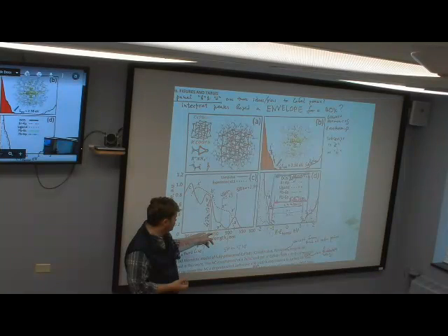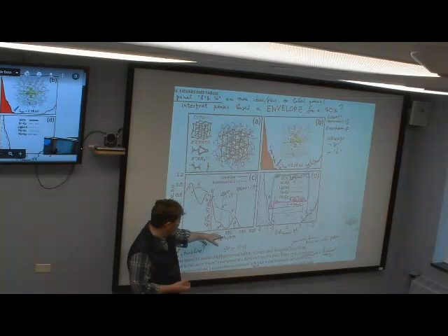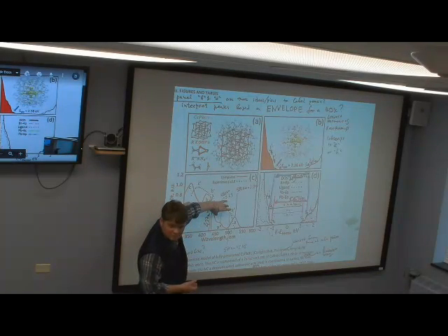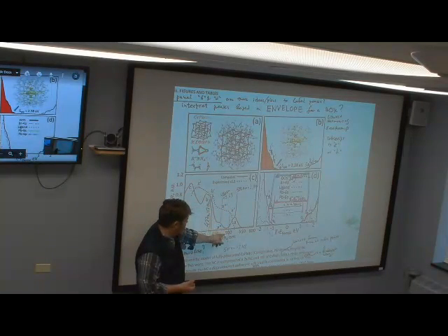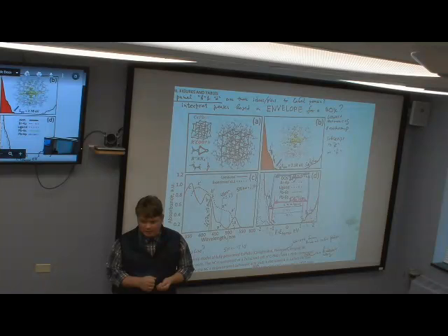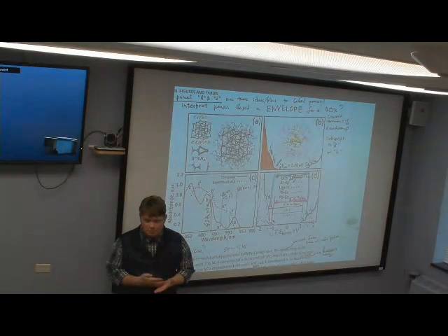So the EDOS is expected to have much higher density in this region, right? But the transitions S to P and P to S are expected to be dark, although there is an abundance of them. It's not super novel, but it is an interesting observation, and it shows that we are on the right track.